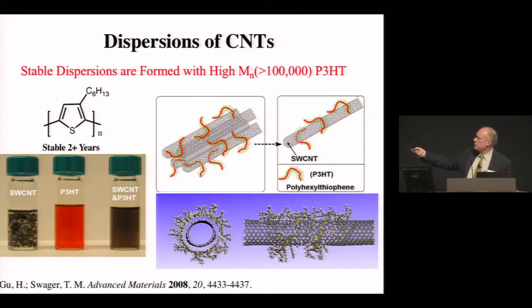And so usually what we do is you'll sonicate them. You use ultrasonic energy to essentially break them apart. And then you'll use something like another polymer here, this is polythiophene, a very highly polarizable polymer that really likes the nanotube surface, that's there waiting around to essentially loop it up and basically create this corona. So this is just a molecular model of polythiophene wrapping it.